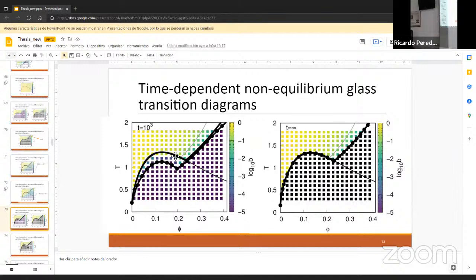Because of the latency times divergence within the spinodal, both lines end up meeting the spinodal and b equals 10 to the minus 1. But that's all that we can say about it. It is an empirical condition for the freezing, but we don't know if it could be used, for example, to observe crystallization. Okay. Well, that's all.